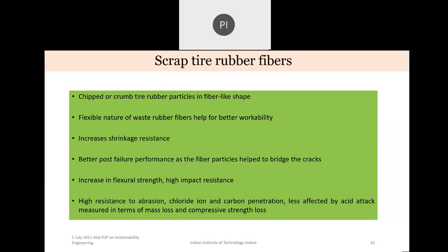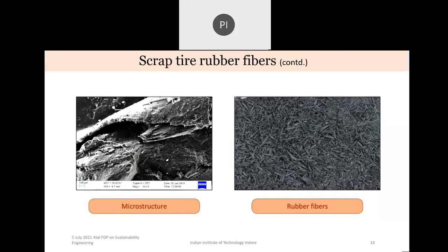And of course, they improve the impact resistance because of their ability to absorb energy. And they also provide us a higher resistance to abrasion, chloride ion, and carbon penetration. And they're less affected by acid attack, which is measured in terms of mass loss and compressive strength loss. So this is the microstructure, and you can see the microstructure of a rubber fiber itself. You can see it has certain cracks in itself. So why it improves the ductility or impact resistance is that whenever we provide energy, first these fibers will crack in themselves. So they will absorb the energy, and the energy taken up by other parts of the concrete will be less.